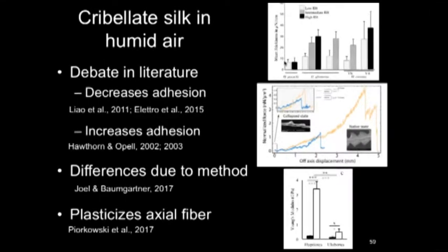And so there's been some debate over the years, but that seems to have been somewhat settled due to possible differences in method, in that using this fine mist may cause large droplets of water and higher water saturation that causes these silks to bind together, rather than if we used evaporated air with lower water saturation, so lower content of liquid water, that may simply allow the interaction with water but not binding.